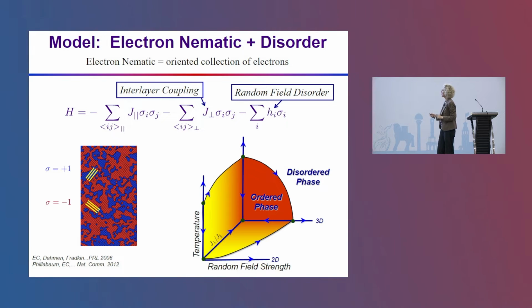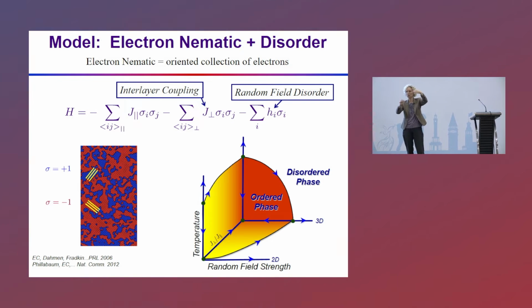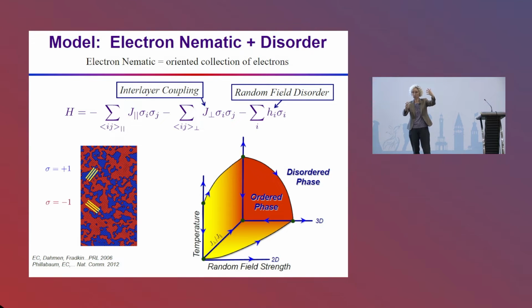So we model disorder here using a random field term, and here's why. The interesting stuff is happening here as a function of doping. And here, doping is chemical substitution. It's uncontrolled, and so it gives you disorder patterns. You can imagine that in any given region of space, there's a pattern of disorder of dopant atoms, and their particular pattern breaks the rotational symmetry of the host crystal. So in one region of space, those dopants would tend to drag the stripes in one direction, and somewhere else they'll tend to drag them in another direction. That's why it couples linearly to the order parameter as a random field term.